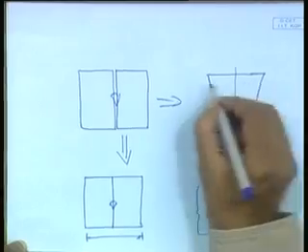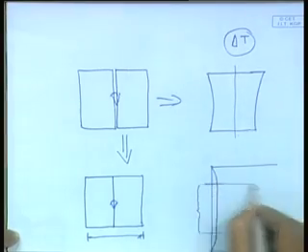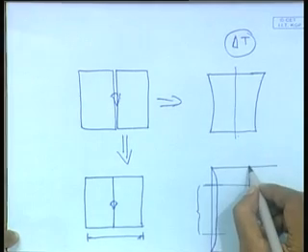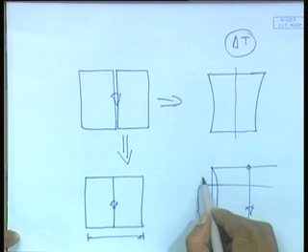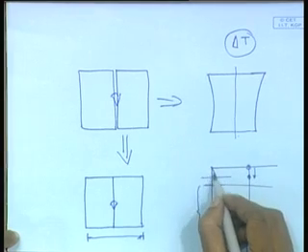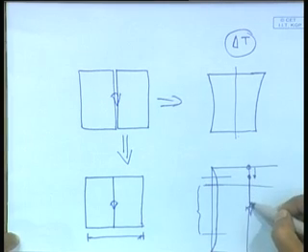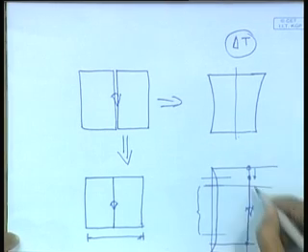This is simply because essentially all the shrinkages, whatever deformations are taking place, are because of the thermal gradient, the differential in temperature, the temperature rise over and above the ambient temperature, right. So it depends on the thermal profile. What happens is at the beginning, say the welding has started from this point. Before it attains a steady state, the welding torch comes up to this point, the transient nature continues. The transient nature continues, which means after this a kind of steady state has been attained up to this point.